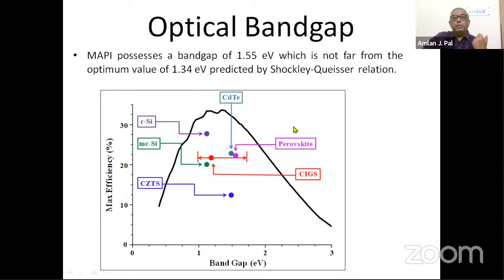And then if you play with the band gap, that is, if you can still lower the band gap of the perovskite material through band engineering, it can still go higher in value. So perovskite is not really a bad material in that sense, in terms of band gap, that it is not above 2 eV or something. So it is really well within the domain where we have all the big shots like silicon, CdTe, and CIGS and other things. So the band gap is really very much within this optimum value of 1.34.